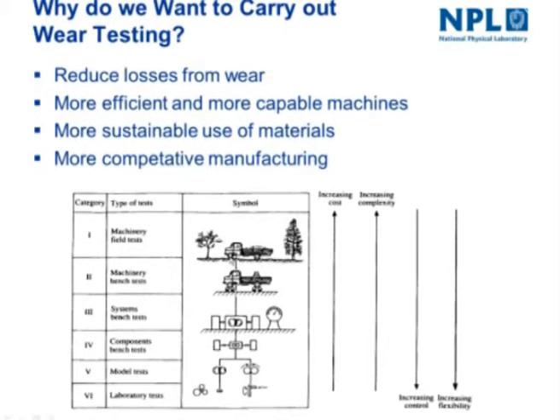I like it mainly because of this diagram of this truck that's trundling through the forest here, and that represents a field test. You've got your system and you actually try it out in practice, and you find after a while it fails, and then you try and work out why it fails. The difficulty with that is that usually it is so complex trying to work out what's happened that you don't necessarily get the fundamental information you want. You can go from that all the way through this sequence of examples to laboratory tests, and laboratory tests are much better controlled. They are cheaper normally. They are less complex. But the big question is, do they really simulate what you want in the field? And that is a very big question.